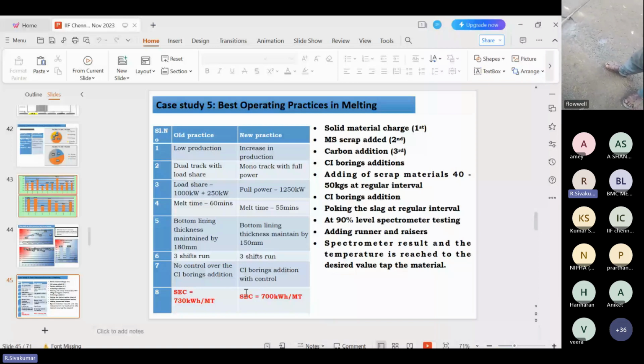So here the material charging is also followed in such a way. Solid material is charged first. Second, MS scrap is added. Carbon addition is third, and then CI boring addition happens. Scrap material of 40 to 50 kgs is added at regular intervals, and CI boring is also added. And the main thing is the poking to be done at regular intervals and the slag to be removed.